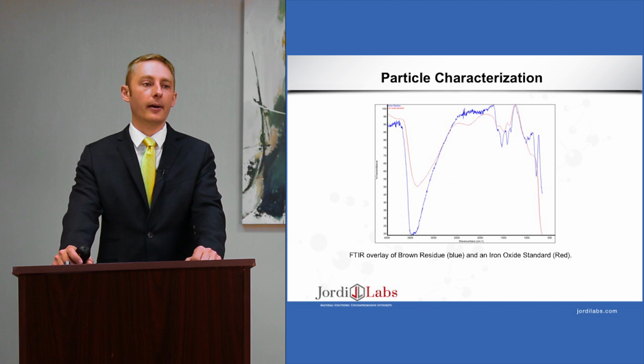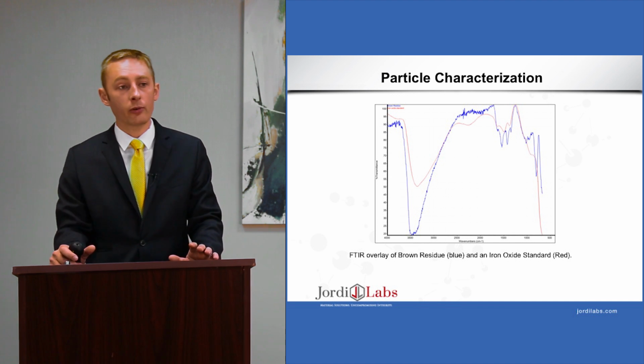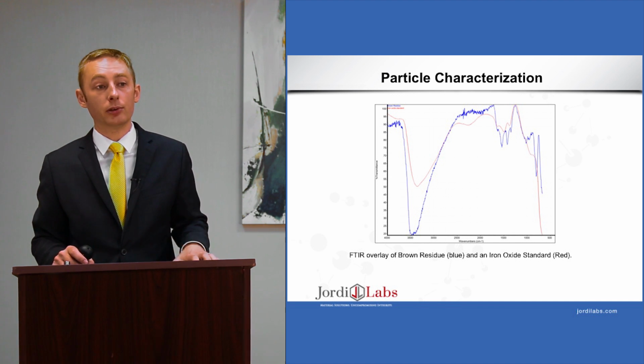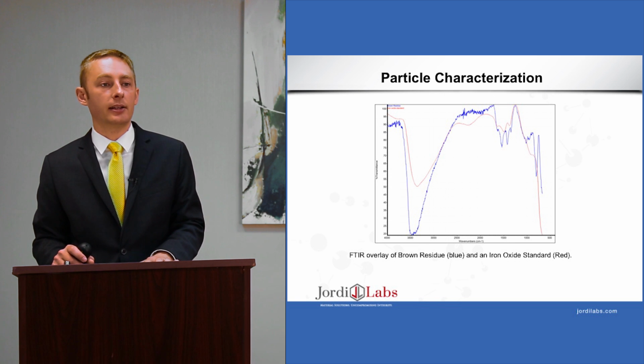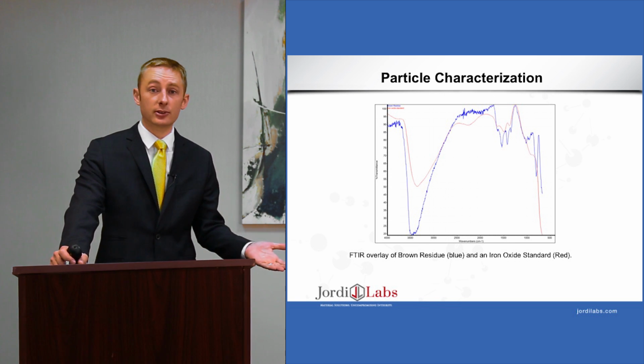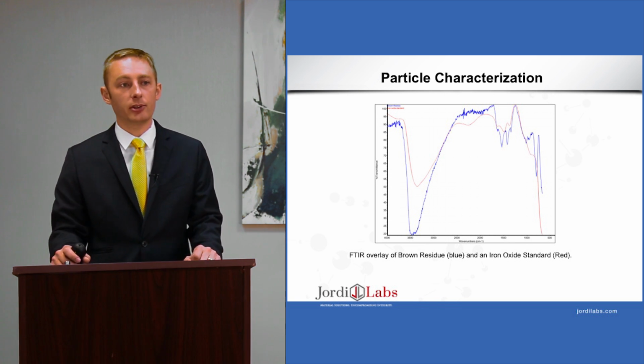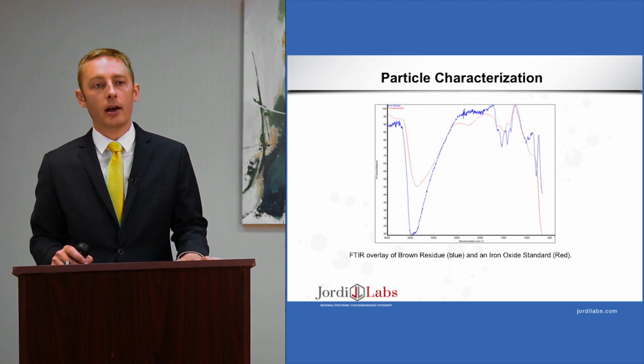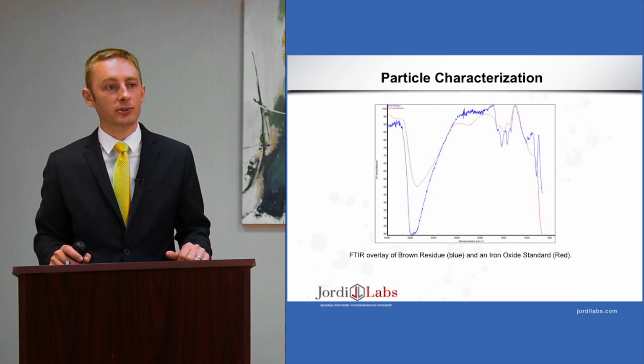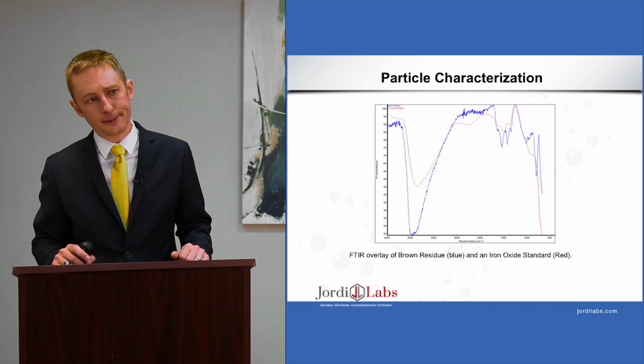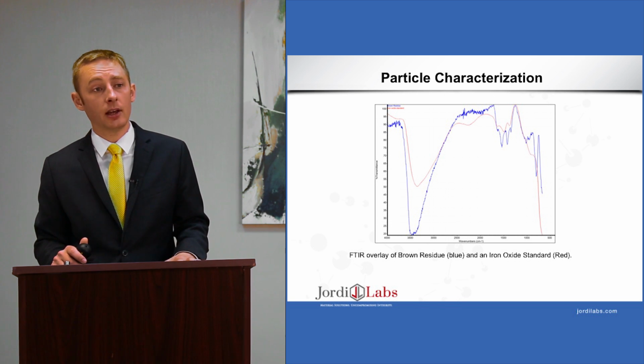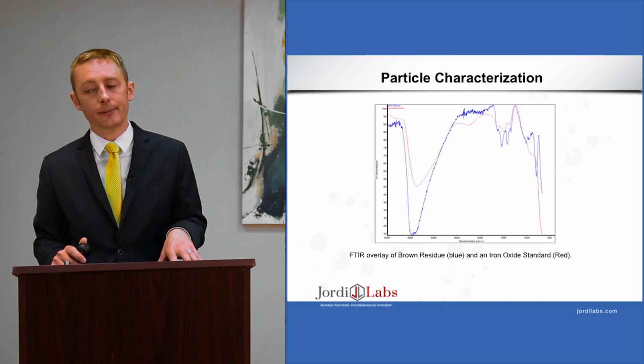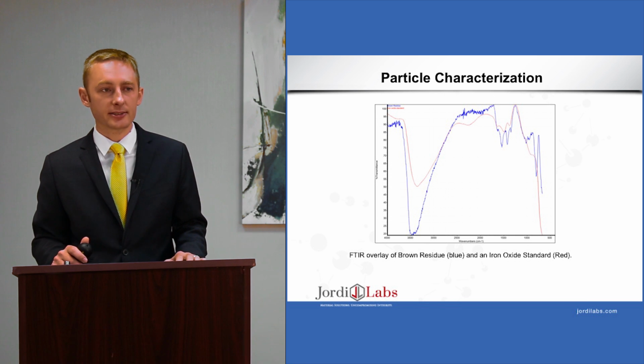Following that up, here's an FTIR overlay of the brown residue in blue, and then an iron oxide standard. We have standards of most kinds of material, not only in our database, but also reference standards of them available to us to image. And it matches quite nicely. So we're pretty sure that this is iron oxide.